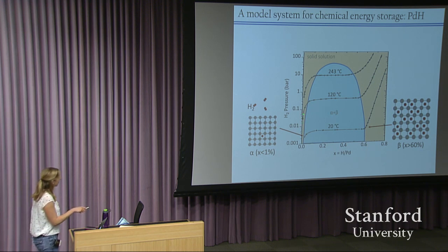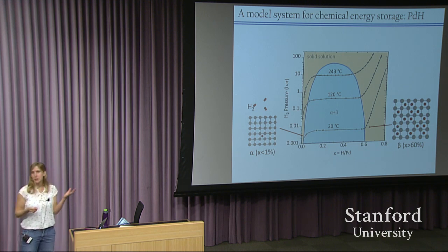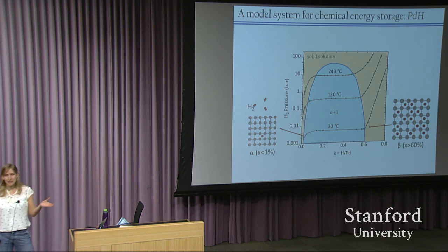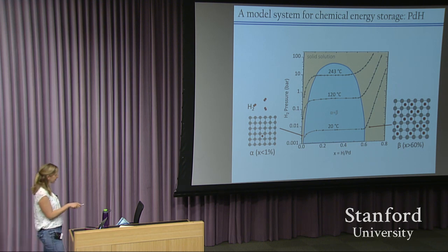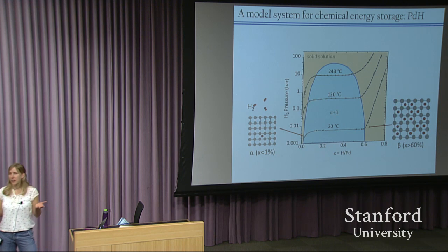So we're in the alpha phase, and then as we ramp up the hydrogen pressure, at one pressure, the system can very abruptly uptake quite a bit of hydrogen, entering what's known as the beta phase. So the beta phase is sketched here. It's generally where, say at room temperature, 20 degrees C, more than 60% of those interstitial sites are occupied with hydrogen. This beta phase is characterized by a pretty significant volume expansion.